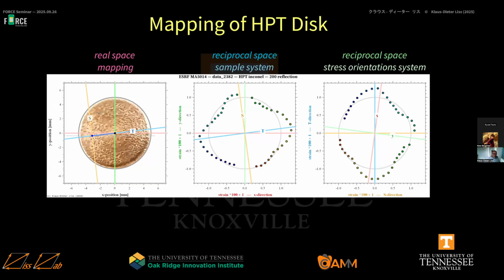Okay, so now let's do the mapping of an HPT disk. This is a typical HPT disk, and we scan, the center is here, marked where all the lines cross, but due to the alignment, it was a quick and dirty experiment, we scan a little bit below that center. And then we can say, remember, the torsion goes in the hoop direction, so the shear stress here is in the hoop direction, and here this line S is the local shear direction in that spot where I'm looking at, this blue spot.